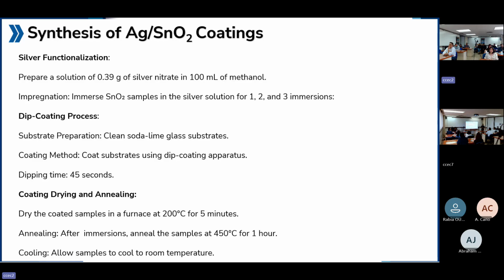The dipping time for each immersion is 45 seconds, and after each immersion, these coatings were dried at 200 degrees Celsius for 5 minutes. Once all the coatings with all 3 immersions were made, they were annealed at a temperature of 450 degrees Celsius for an hour. After annealing, these coatings were slowly cooled at room temperature.